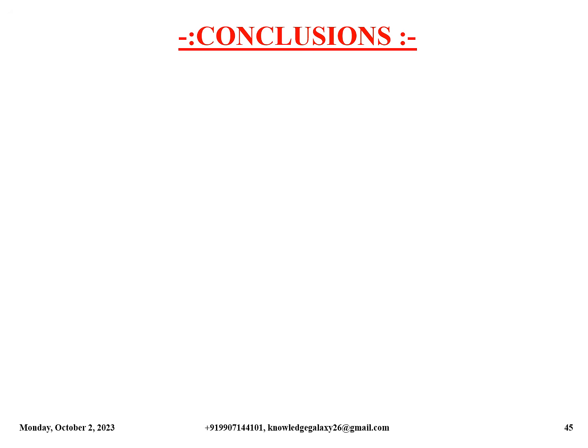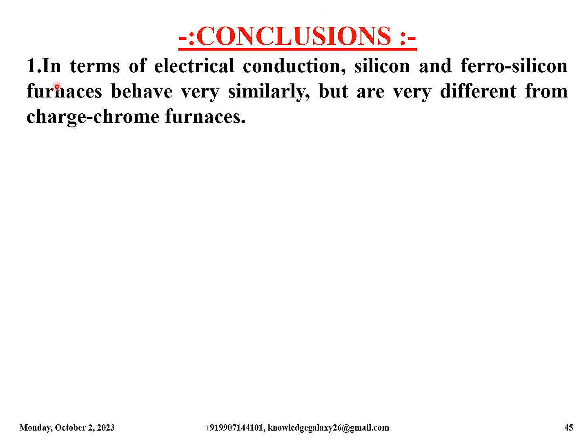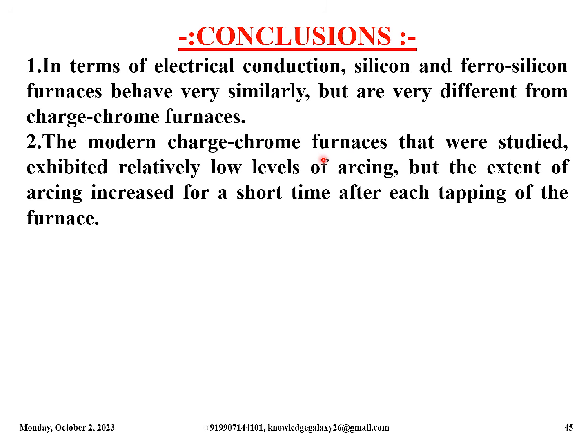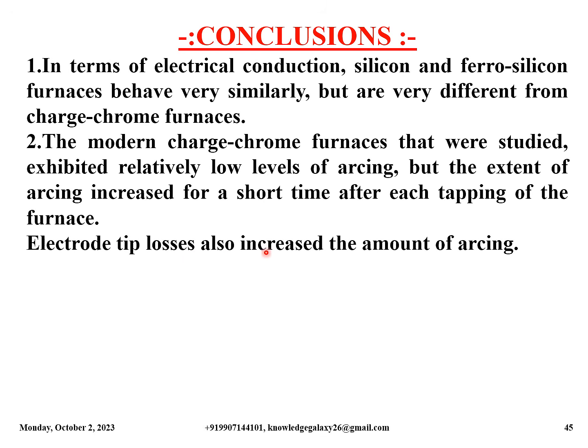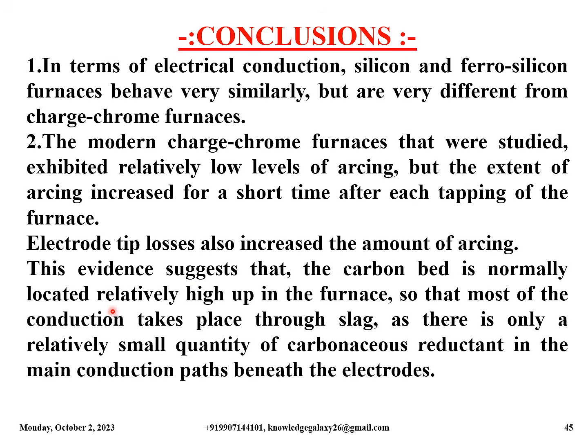Now let us have some conclusions which are based on these studies. First, in terms of electrical conduction, silicon and ferrosilicon furnaces behave very similarly but are very different from charged chrome furnaces. The modern charged chrome furnaces that were studied exhibited relatively low levels of arcing, but the extent of arcing increased for a short time after each tapping of the furnace. Electrode tip losses also increased the amount of arcing. This evidence suggests that the carbon bed is normally located relatively high up in the furnace, so that most of the conduction takes place through slag, as there is only a relatively small quantity of carbonaceous reductant in the main conduction path beneath the electrodes.